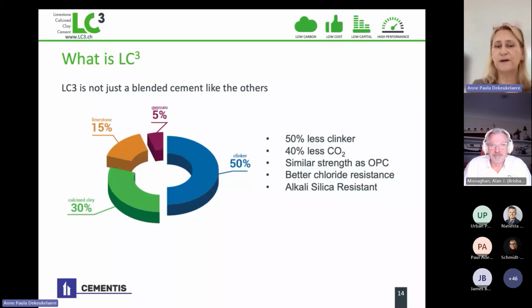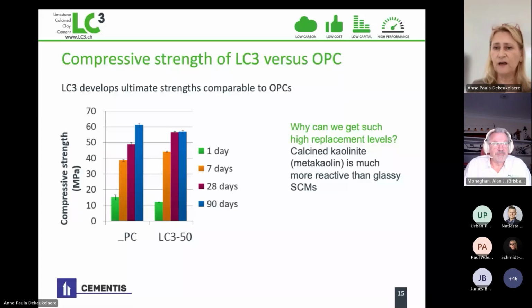This was to compare the strengths development of OPC and LC3 with 50% clinker. We really have nearly no differences. So which means that we can use LC3 very quickly and change any cement by LC3 and use it like any other cement. So that was really the positive side.